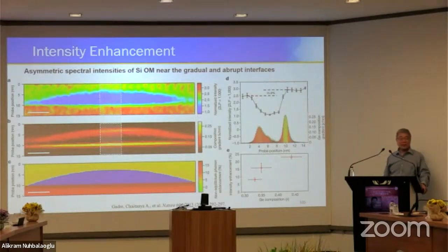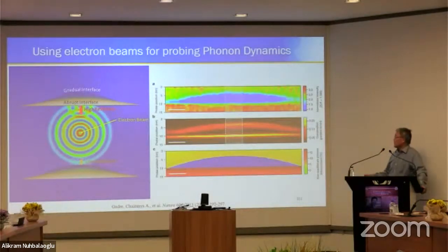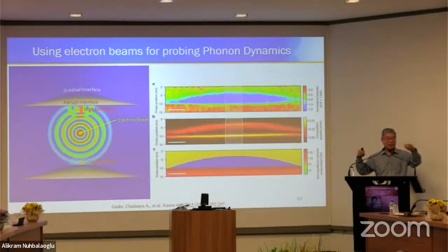So we try to understand why. That means you have more phonons on the side of each interface, but the enhancement is at a different degree with the two different parts of the interface. So we try to understand this, and then we think about a very simple model. Electrons will be able to measure phonons, but an electron with high energy is also able to create phonons, because it loses some energy to the lattice and they generate new vibration.